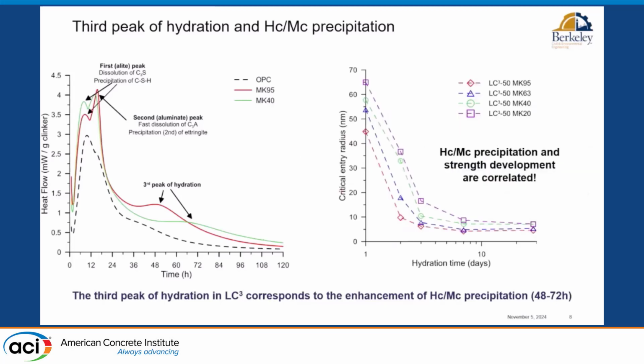And this is very interesting because this is exactly the same period of time when we see that the porosity of LC3 plunges, and we have this refinement, as people like to call it, of the microstructure where we go to these very, very small critical entry radius that we can measure by MIP. But in a sense, we still have a disconnection between kinetic features that we can observe by calorimetry or XRD and the mechanical world, which is more related to porosity.